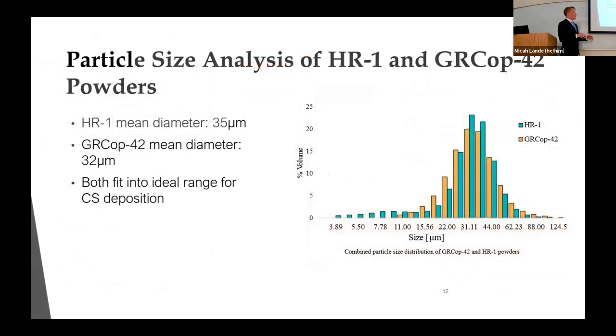So again, starting at the ground level, we want to first see what we're looking at, if it's even in the size that we want. So doing some particle size analysis. For cold spray, traditionally, you want those particle diameters to be between about 10 and 50 microns wide. As you can see here, the majority of our distribution falls in that range. There are studies that have shown that for cold spray processes, having smaller particles trending towards that 10 micron range is better, but again, you have an increase in manufacturing costs to reliably make sure that all your powder particles are that small. So again, this shows that we're in the ideal range for cold spray.